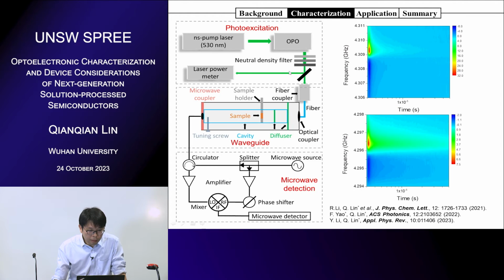So this is the setup of our TRMC measurement. We have photo excitation with a nanosecond laser. We can also use a femtosecond laser, and we can tune the wavelength and the light intensity easily from here. And here's the microwave cavity. So we put samples within the microwave cavity, and we can increase the sensitivity quite a lot. And for TRMC measurement, the sensitivity is normally much higher than terahertz. And we also have a microwave detection system here.